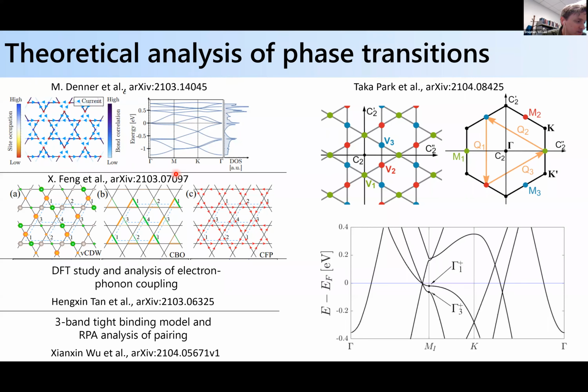There's no momentum-resolved scattering type of measurement that could distinguish between these. I think the experimental evidence currently is founded in the STM data that sees some type of dominant Q vectors that switch in the 3Q order as you switch the direction of the magnetic field. I think that's one driver. The other is the muon spin rotation data that suggests something is happening magnetically, because you see a jump in the relaxation rate in a transverse field measurement.